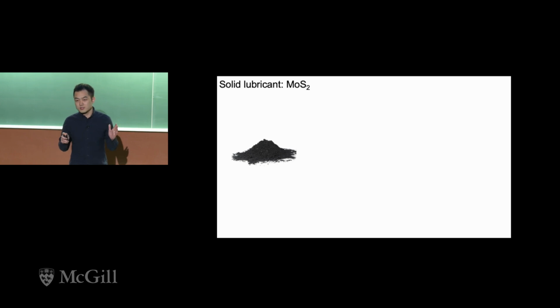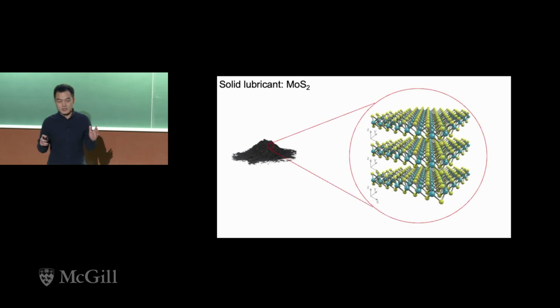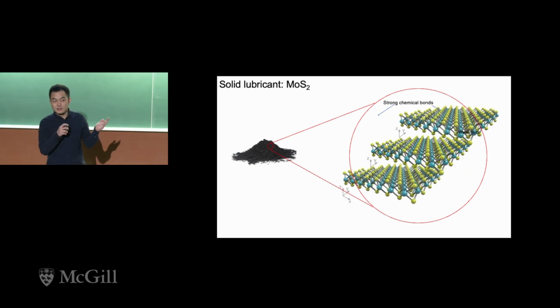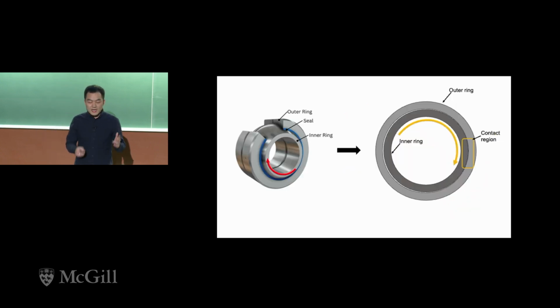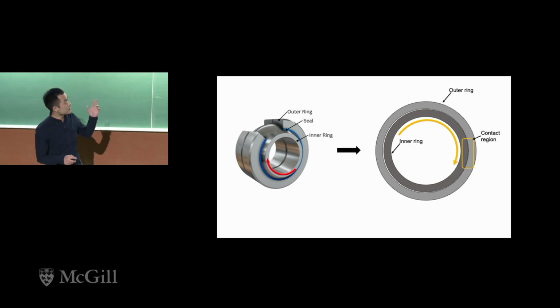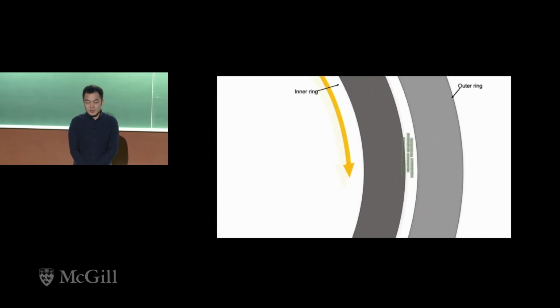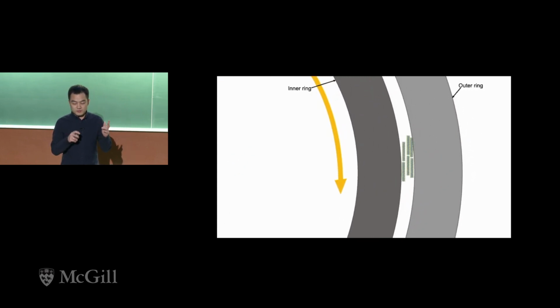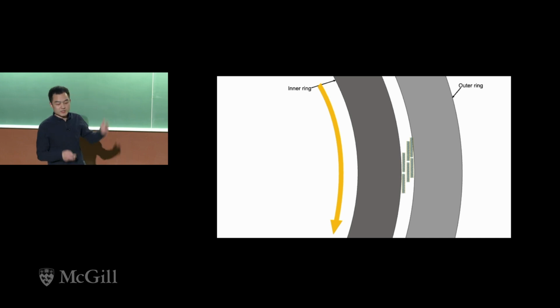MoS2 is a commonly used solid lubricant in space, and we call it lamellar or layered material because it has atomically thin planes that are very strong, but the actual force between those planes is very weak. That means they can slide over each other really well. When adding it to some frictional components, let's say a bearing system, what happens to the contact region is, as the inner ring rotates, those planes separate the real contact surface and slide over each other with very low friction, so the inner ring can rotate pretty smoothly.